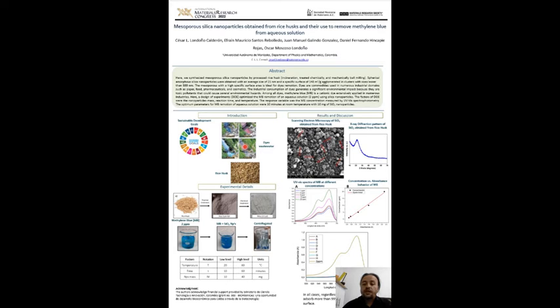Among all the known adsorbents, silica nanoparticles have been considered promising nanoadsorbents due to their particular characteristics, such as low cost, simple synthesis, low environmental damage, stable structure, high specific surface area, and porosity. Adjustable pore size and volume. This type of nanoparticles can be obtained from rice husk, which is an agro-industrial residue that is generally wasted or incinerated to get rid of it.